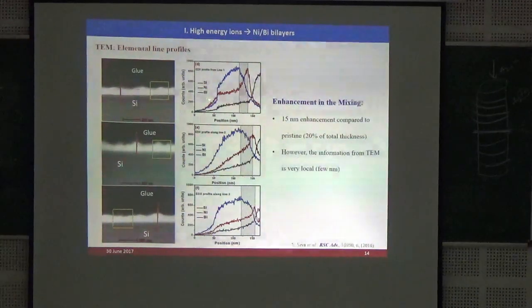So for silicon, nickel, and bismuth are shown here. We have drawn a window of cross lines to emphasize the intermixed region of nickel and bismuth. Here you can see with increasing ion fluence, the width of this window is increasing. It is almost 15 nanometer of enhancement with increasing ion fluence, which is actually 20% of the total thickness of the film. However, the information from TEM is very local. So in order to confirm whether it is there throughout the sample or not, we need to perform RBS measurements.